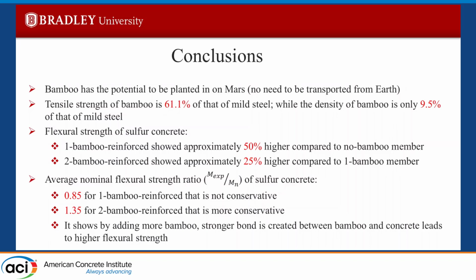And then our final conclusion was the average nominal flexural strength of sulfur concrete with one bamboo is around 0.85, which means it's not that conservative, but as you increase it to two, it jumps to 1.35, which makes it more conservative, which essentially shows by adding more bamboo, there's a stronger bond within the specimen itself, and it leads to a higher flexural strength, which overall proves that as you add more bamboo, it works better for the sulfur concrete.